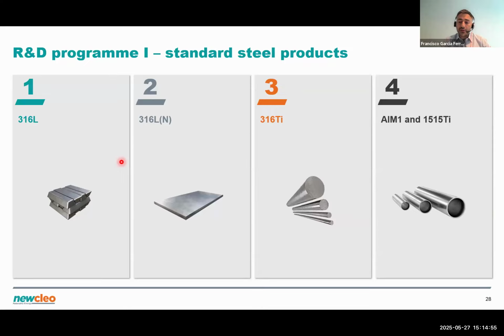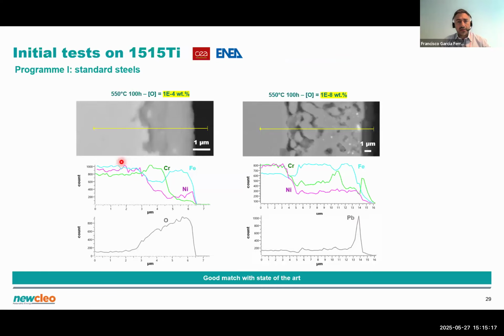It's very important not to think of materials purely as a given chemistry, but also a given chemistry with a certain heat treatment, a certain microstructure, a certain manufacturing route, and a given geometrical shape. So those are the elements we intend to work on. And in that sense, we already did a number of tests here. I'm just showing an example where we investigate some transients and so on, different oxygen contents, and so far we managed to reproduce essentially the state of the art, having either oxidation or dissolution depending on the oxygen concentration. This is work done in collaboration with ENEA and CEA.